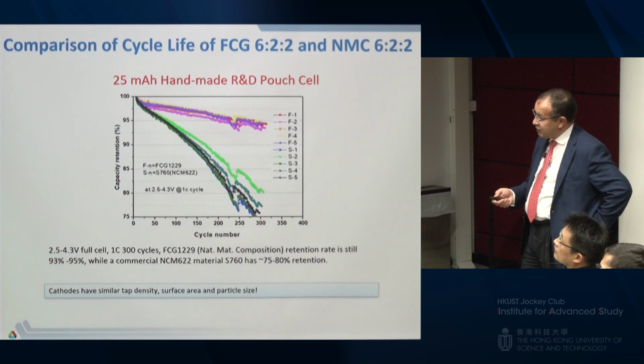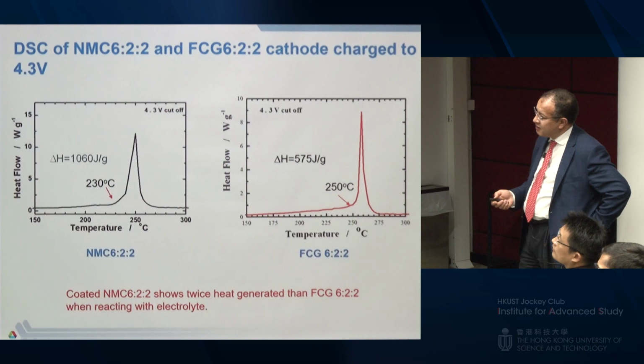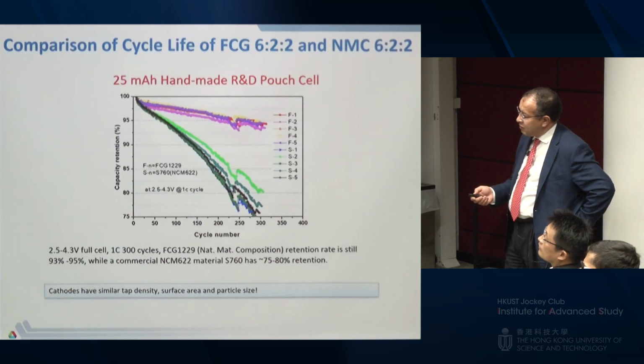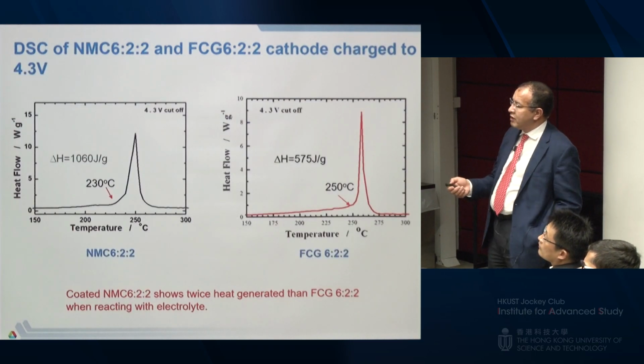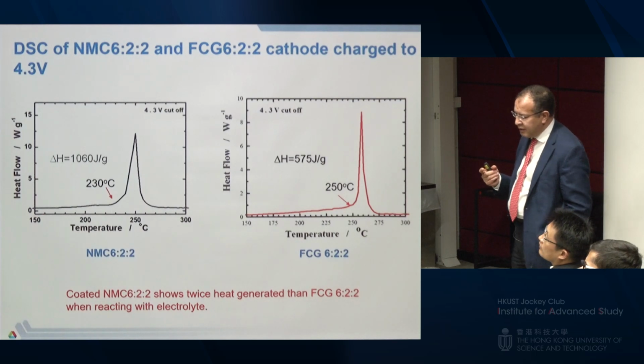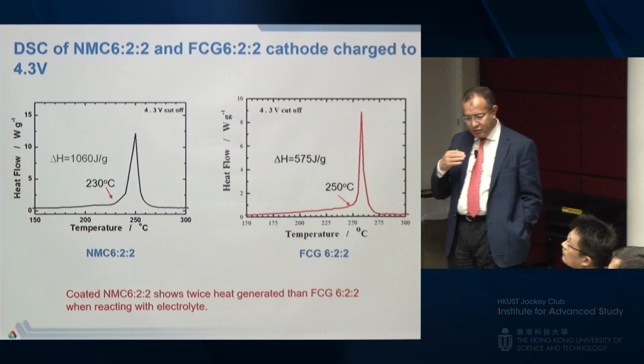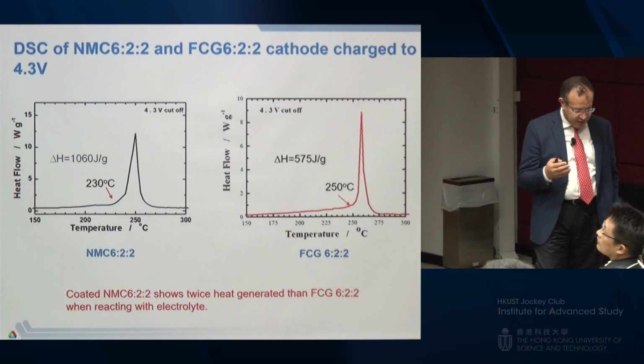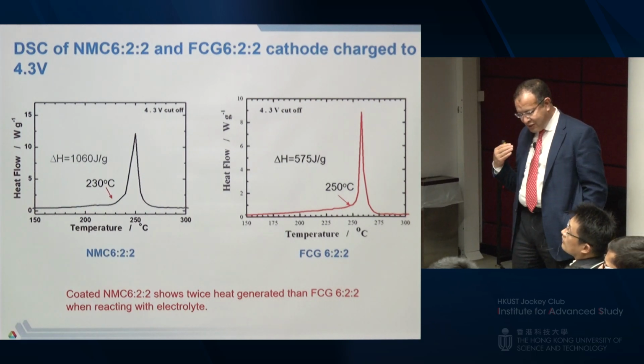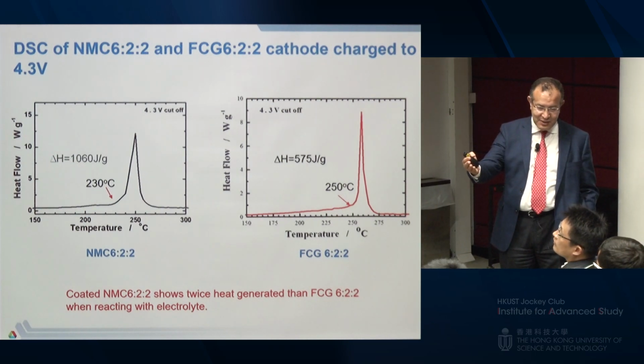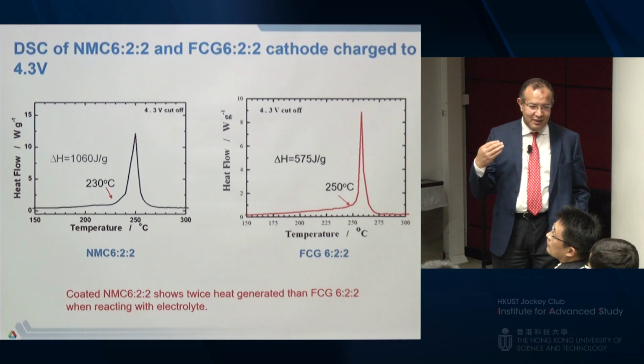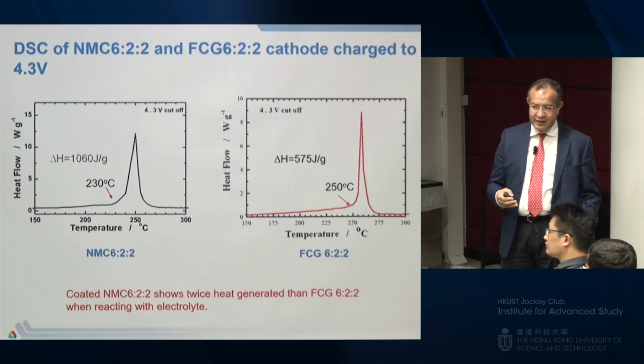We also work with the industry and build bigger cells. Well, let me show you. Of course, one of the other reasons why we're trying to stabilize the surface is to enhance the cycle life, but also enhance the safety, because oxygen reaction with the electrolyte is exothermic, and therefore you can create a thermal runaway if you don't control it.